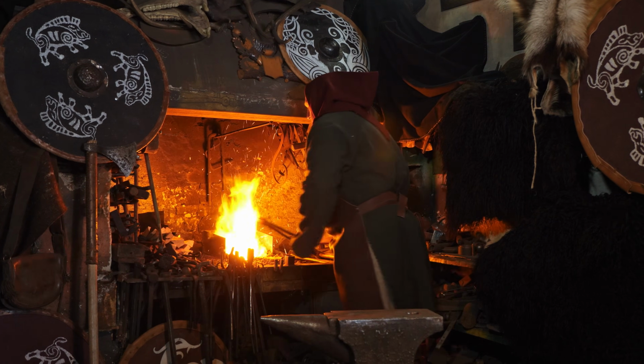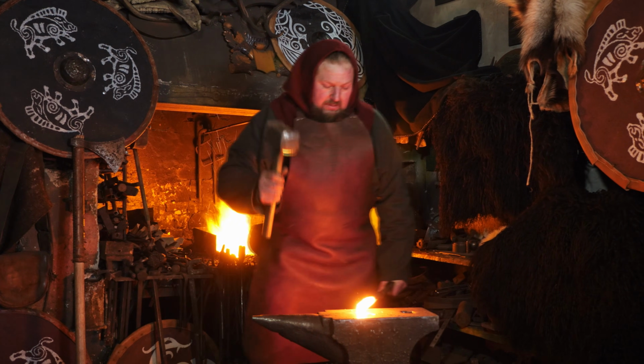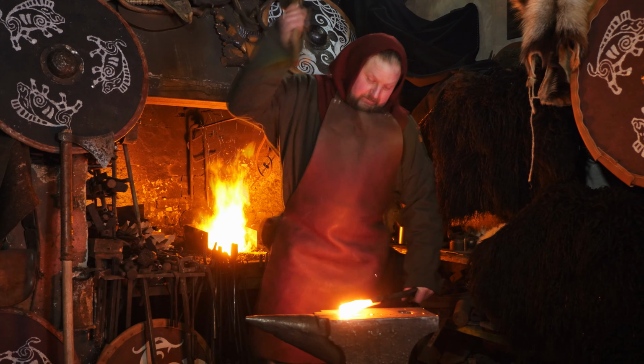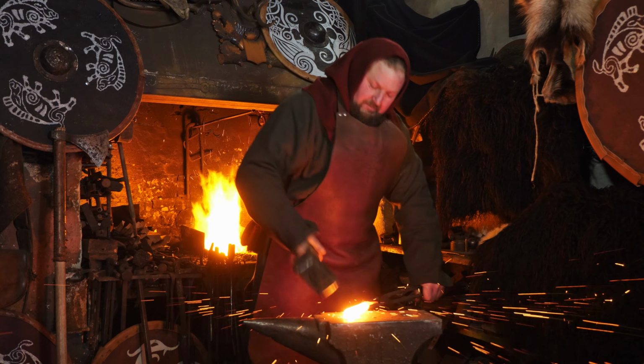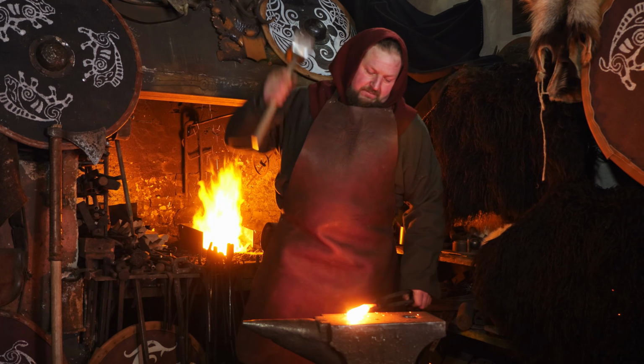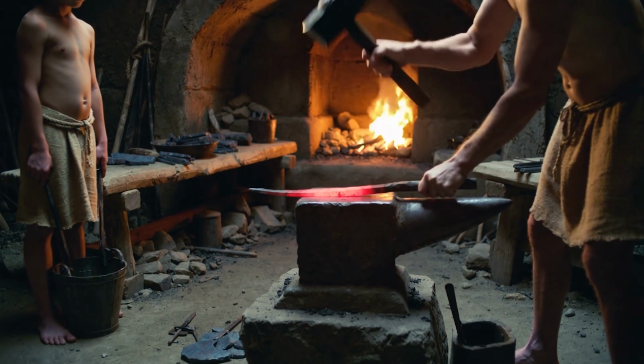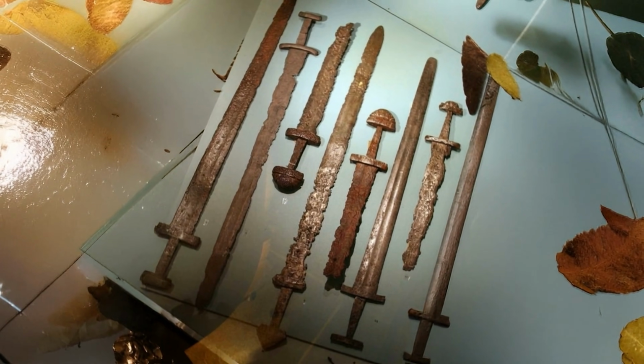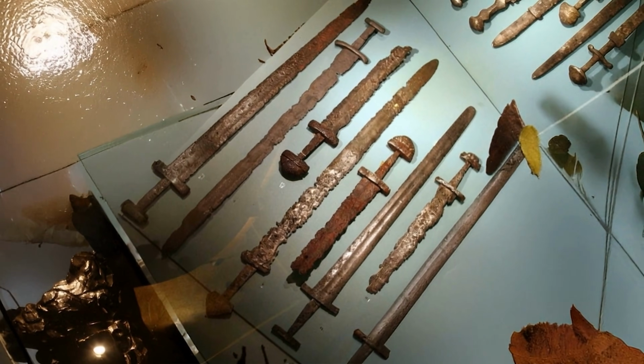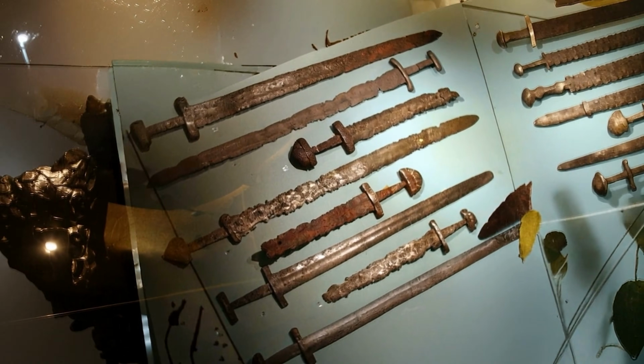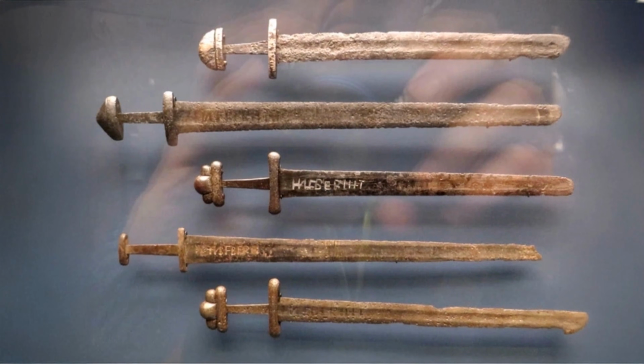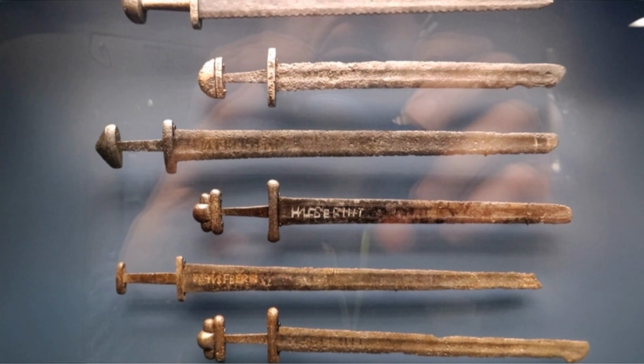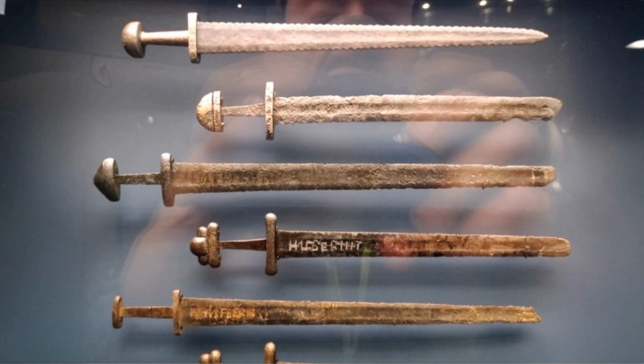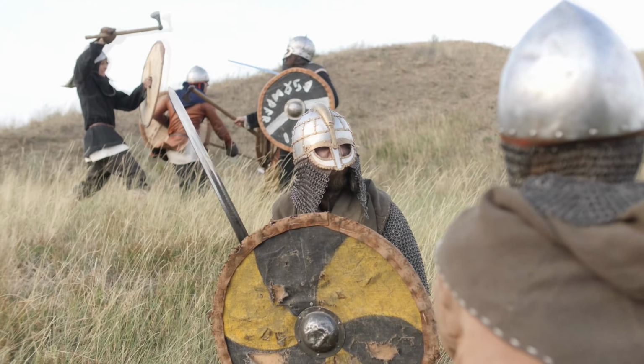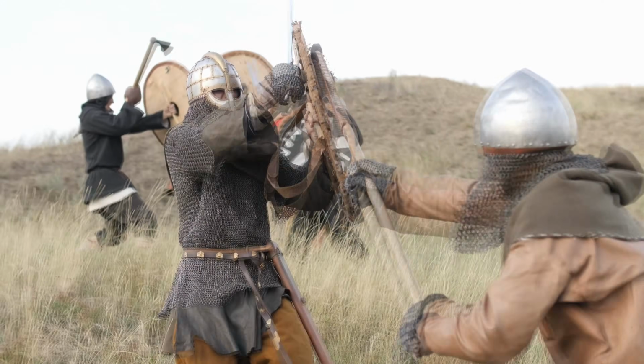Metallurgical analysis has shown many of them were made from crucible steel, a material far superior to the bloomery steel common in Europe at the time. Crucible steel was produced by melting iron with carbon under controlled conditions, creating a pure, uniform metal capable of holding an exceptionally sharp edge. Several Ulfberht blades tested by researchers exhibit carbon contents comparable to later medieval and even early modern steels. Their microstructure shows minimal slag inclusion and a high degree of homogeneity. This steel was far more resistant to breakage and deformation than typical Viking swords, which often required pattern welding to compensate for inconsistent iron quality.